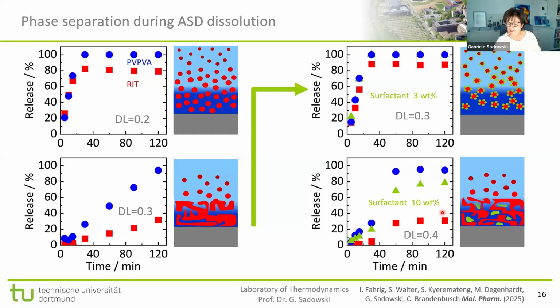So what about the morphology back? And what we see, and I will show you the Raman map on the next slide, is if the amount of surfactant is too big, it forms a third phase. Instead of stabilizing the droplets in a two-phase system that we had at low surfactant concentrations, we now, as we have 10 weight% of surfactant, have three phases forming.